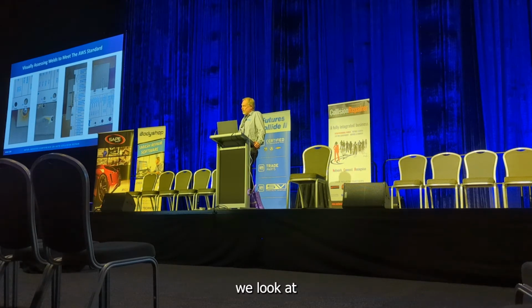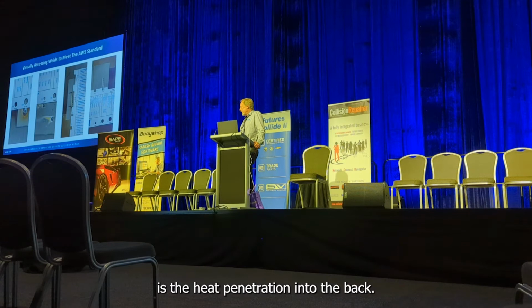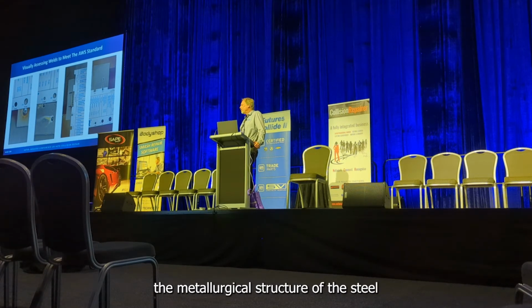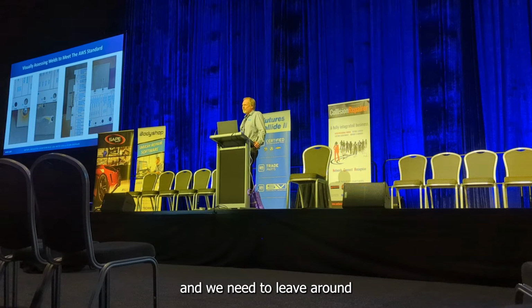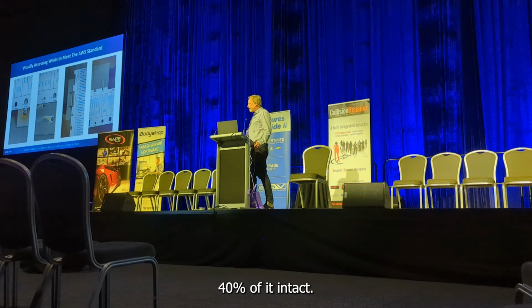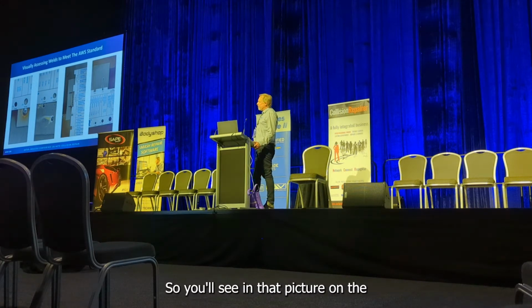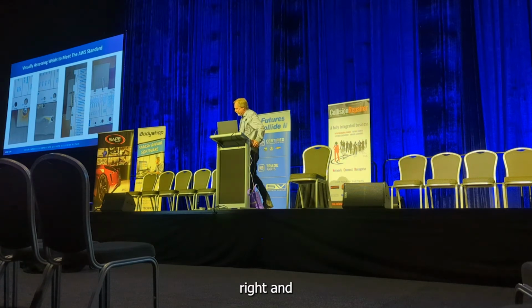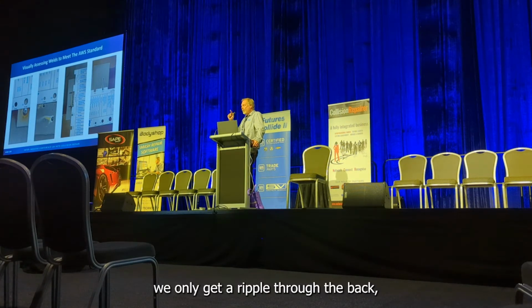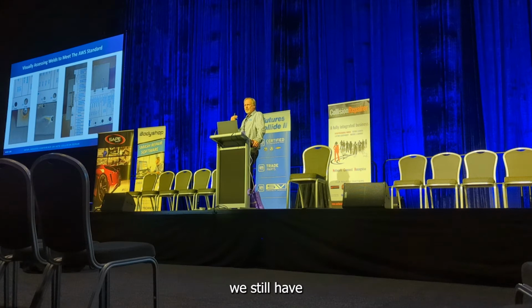One of the biggest things we look at for any of the visuals is the heat penetration into the back. The heat effect zone is critical because we can't afford to damage that metallurgical structure of the steel too much, and we need to leave around about 40% of it intact. So you'll see in that picture on the right, we only get a ripple through the back, which means we still have metallurgical structure intact.